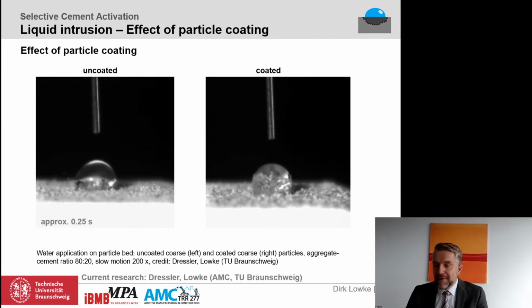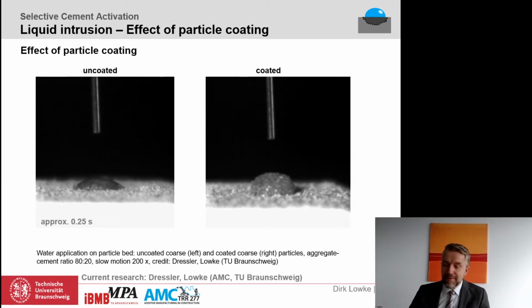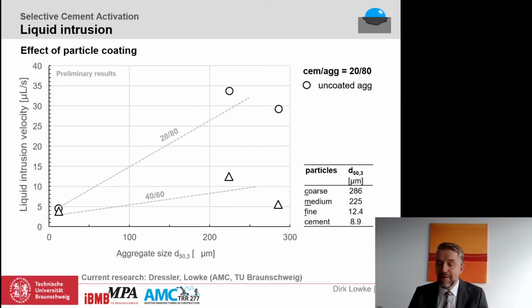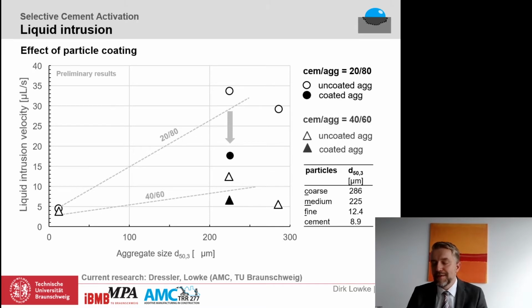And you can see, firstly, that the sand particles are somehow moving on the surface of the water droplet. And if we go further on in the video, then we can see that the intrusion velocity significantly decreases when the sand particles are coated with a hydrophilic silica fume. In terms of numbers, the penetration rate is halved from 34 microliters per second to 17 microliters per second.